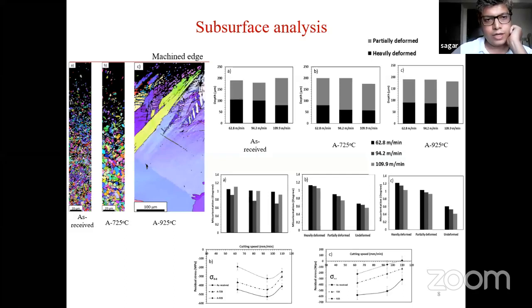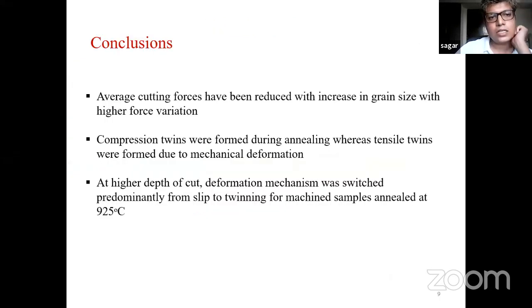So in a way we could say that increasing the grain size could lower the cutting force, meaning it could lower the power consumption also. However, it could increase the variation on the cutting tool. And in case of titanium machining, the cost of machining is driven by the cutting tool predominantly. So these are the conclusions from this area. I have two more areas to cover. So the average cutting force has been reduced.